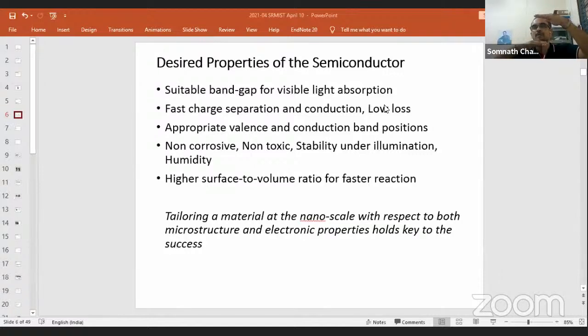That's fine. Now let's say I have this gap, the band gap. This gap is also suitable for visible light absorption. Now let's say I have a material where this gap is good, but this is somewhere here, this is somewhere down. I mean, these reference levels I'm talking about in terms of electrochemical energy, or let's say vacuum energy. So I need to have this conduction band at a certain position, this valence band at a certain position, plus this gap also. So all these conditions need to be fulfilled, which is really challenging for a single material.